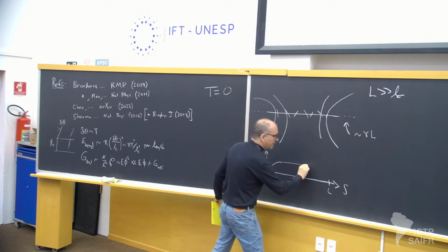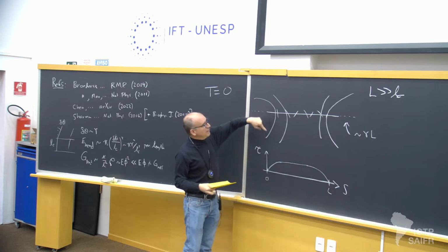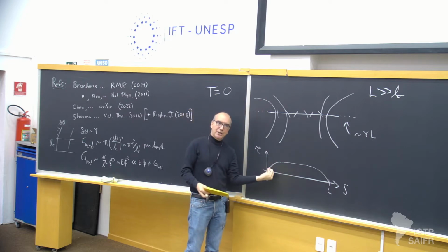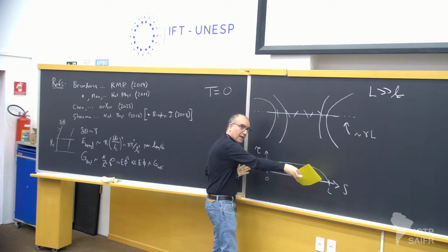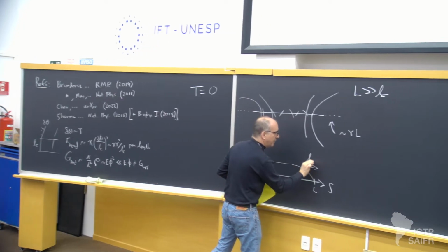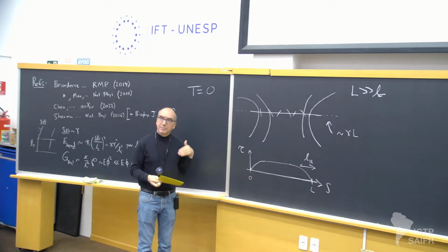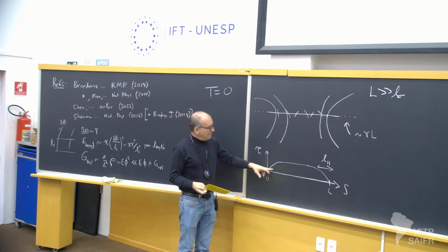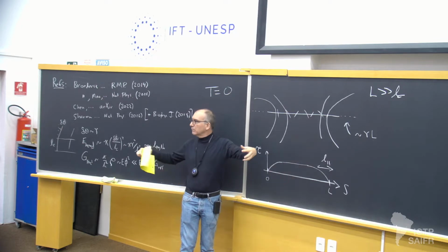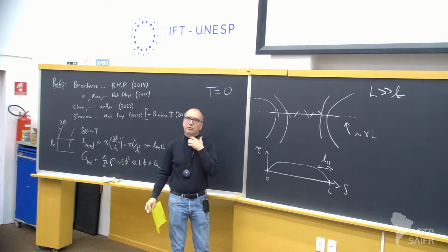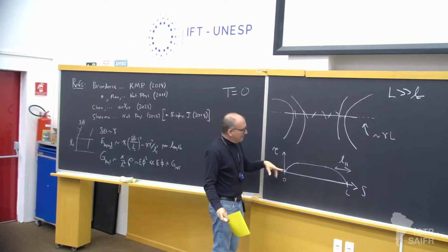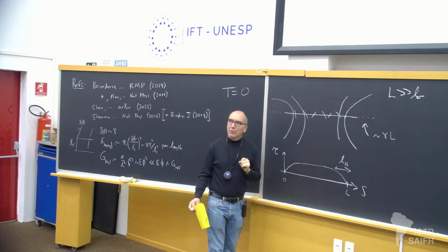And then near the ends, if I balance the bending energy associated with all this deformation, I'll get a zone over which the contraction can occur, not over the full fiber length, but over a region. So there'll be a new length scale that appears. I'll call it L parallel. It's going to be a longitudinal length. And this happens to be what simulation also shows if you simulate high molecular weight fiber networks, in 2 dimensions. Or, well, let me hold off on 3 for a bit. Okay, so it's that limit of high molecular weight I want to address.